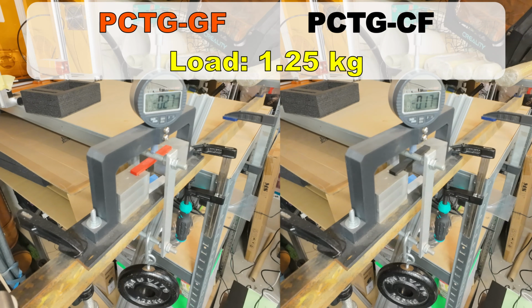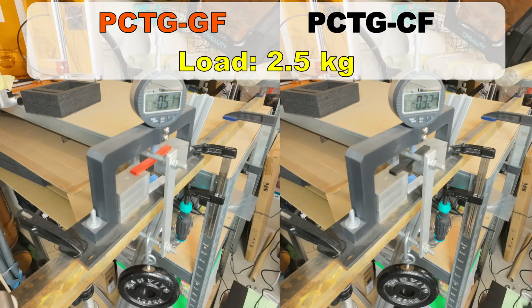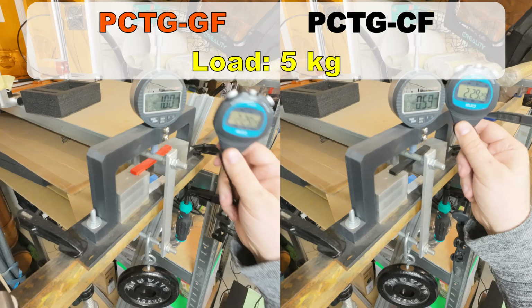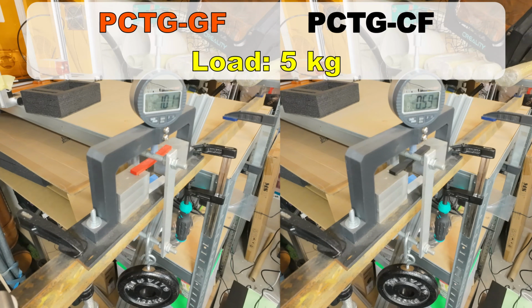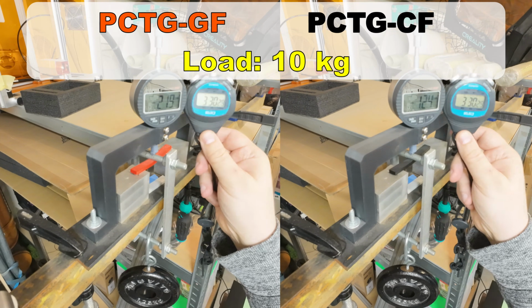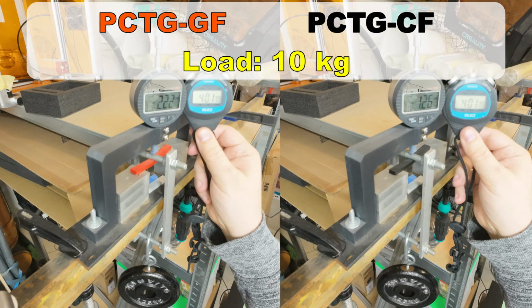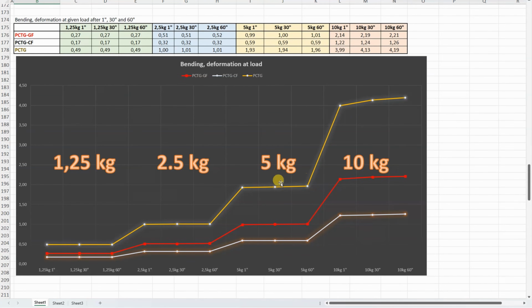3-point bending test. Distance between supports is 50 mm. And I am placing these loads one by one, and I am measuring the deformation after 1, 30 and 60 seconds. Currently you can see the deformation under 10 kilograms. Well, something we could even predict because fibers make the parts stiffer, and between these two, carbon fiber version is stronger, and very minimal deformation even under 10 kilograms during this 1 minute.